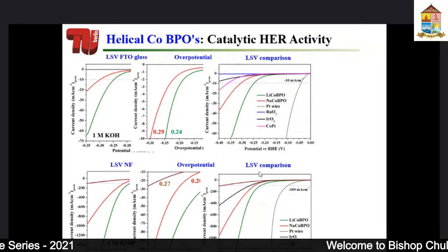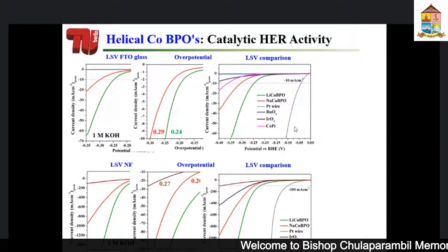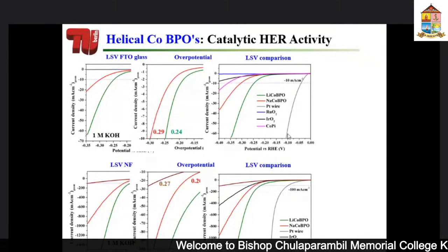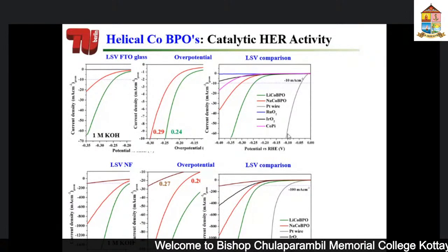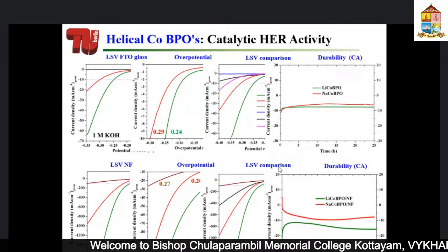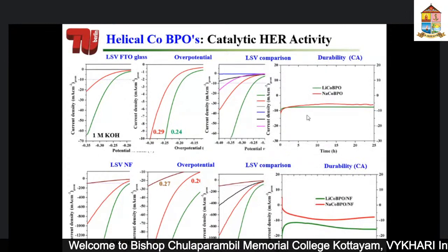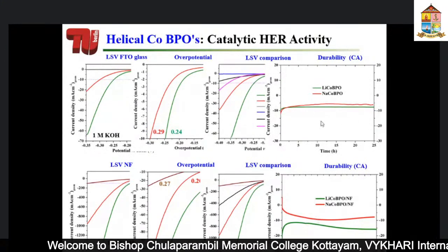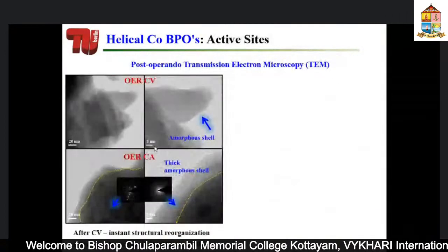So again, we compared our material with other known materials, and we see that these materials are much more active, not as good as platinum, because platinum is an excellent catalyst for hydrogen evolution reaction. It is very difficult to come even close to platinum catalyst, but as I said, one of the other ways is to enhance the performance of the oxygen evolution reaction so that we can drive this reaction more efficiently. Again, we conducted stability tests, and as you see, they are very stable. So there's no problem with the stability.